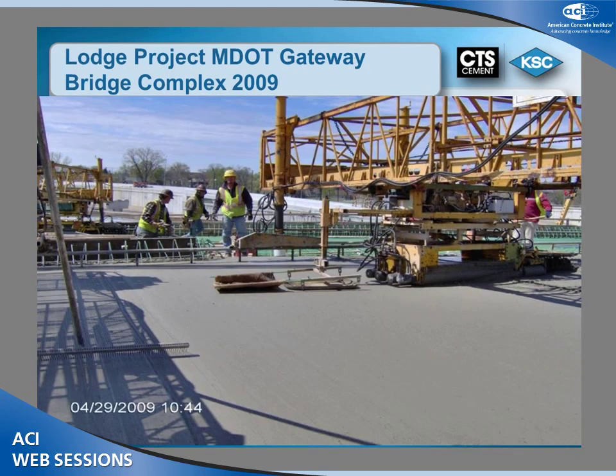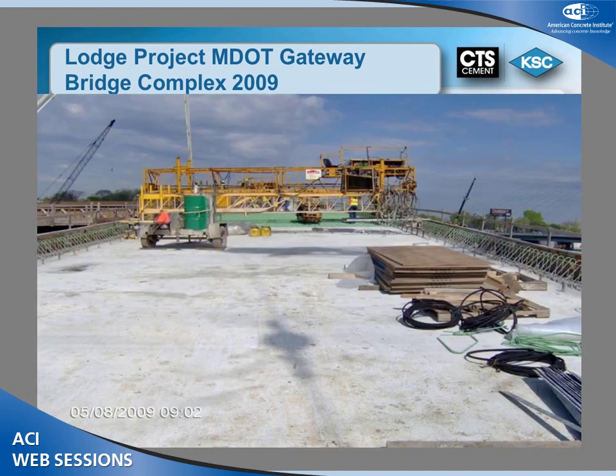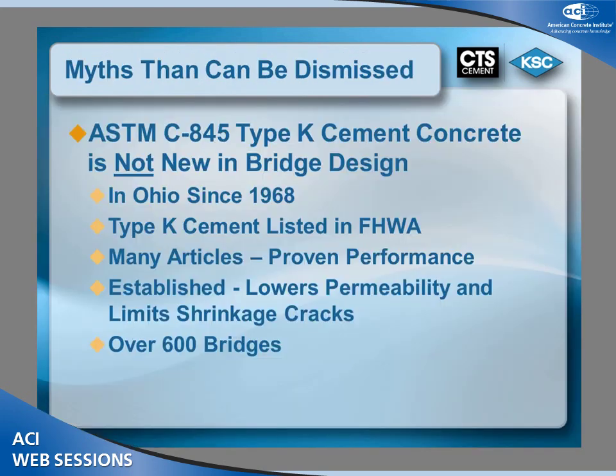Again, back to some of the equipment. This is a standard bridge deck machine. It's self-propelled, can move backward and forward, and works quite well. And what's really nice is that these shrinkage compensating cements actually have a finer blade, and we end up with a little creamier texture to the concrete. So the machines actually move across and the closure is very nice. Just a quick picture, this right here was basically 7 days after the placement of this one section.